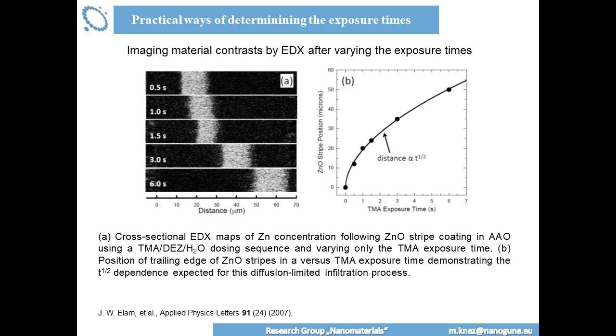And the location of the diethyl zinc is here, which means that the initial exposure time to aluminum oxide, or to TMA, of 6 seconds led to a coverage up to here. And you can measure the depth of the aluminum deposition before the zinc deposition. And in this way, you can derive the traveling time of the precursor into the pore. You can derive then the diffusion coefficients which you want to have. So it's a little bit of a complicated methodology, but it's quite interesting to go with that.